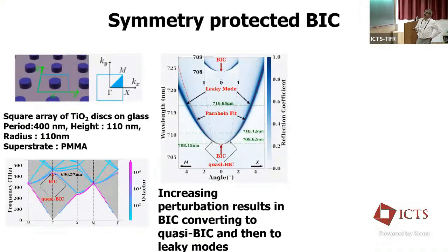So we showed a symmetry protected BIC. As I said, this only happens for normal incidence. These are TiO2 pillars or discs on top of a glass substrate. At normal incidence, you have zero line width. This is a BIC resonance. If you change your angle, you go to high Q, but not infinite, with finite line width modes, which are called quasi BICs. And if you go further away from normal incidence, you see these leaky modes, which couple to the far field, and they have much smaller Q factors in this case.